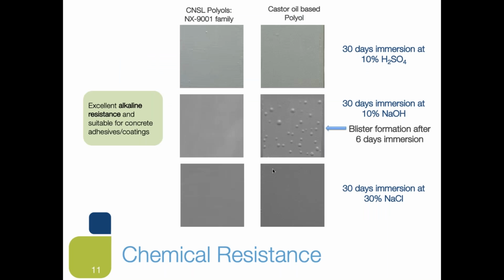We have also studied the chemical resistance of key polyols. In this case, the NX9001 family in comparison to castor oil-based polyols. The prepared panels were exposed to acid, sulfuric acid, alkaline, sodium hydroxide, and salt for 30 days. Both products have shown excellent performance in acid and salt, but the castor oil-based polyol showed blister formation after only 6 days immersion, whereas the CNSL-based NX9001 family did not show any defect. So it's showing the best alkaline resistance.